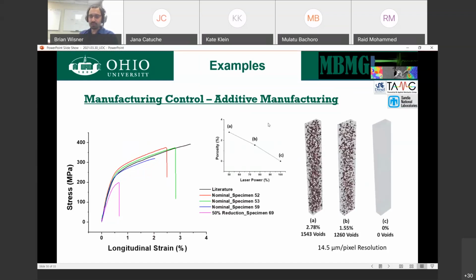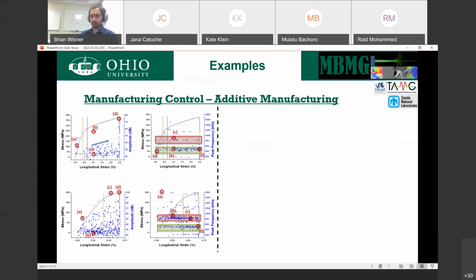To give you an idea, starting with nominal, 25% reduced power, 50% reduced power, we have less material bonding. We have more pores, more lack of fusion defects. Makes sense. What we also see is a significant change in how the material fails. The properties are very different. In nominal, we have very good plasticity in zones. In 50% reduced, we don't. It basically yields and breaks. What was interesting was the fact that you have so much more AE activity in the 50%.